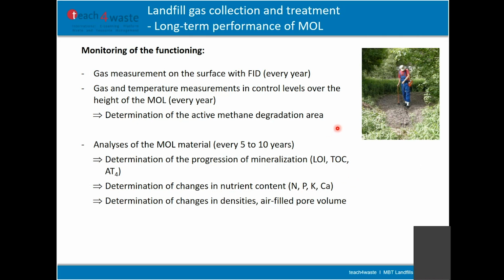They have a lot of experience also over longer time. So you have to monitor it. As I said, you have to make at least one surface measurement every year with FID, this detector. With this detector, you can only see if there is methane or not and the concentration, but you cannot determine the flux. Only the amount of methane in the air can be determined. So on the surface, you should also have a look in the methane oxidation layer itself, to have a look at temperature and maybe also take some samples to analyze the gas concentration.